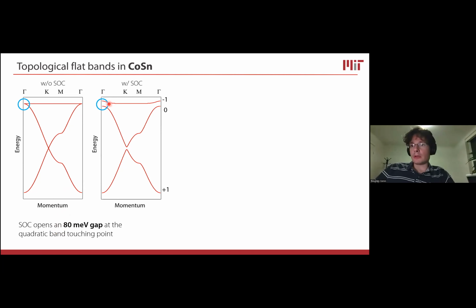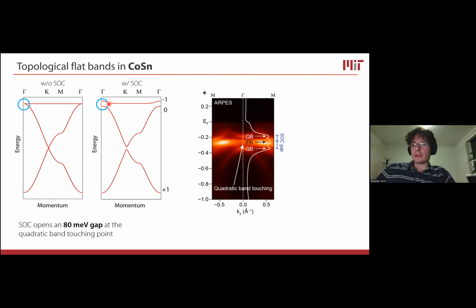at the gamma point, there is a gap that opens up that has a magnitude which we really didn't expect. So we observed a spin orbit gap, which is as large as 80 milli-electron volts between the flat band and the underlying Dirac band that reaches the gamma point and forms its quadratic band touching point. And so this gap arises from spin orbit coupling. It is predicted by DFT to happen at the gamma point. We have really no good understanding of why it is so large, considering that the atomic spin orbit coupling of cobalt is not nearly as large as 80 milli-electron volts.